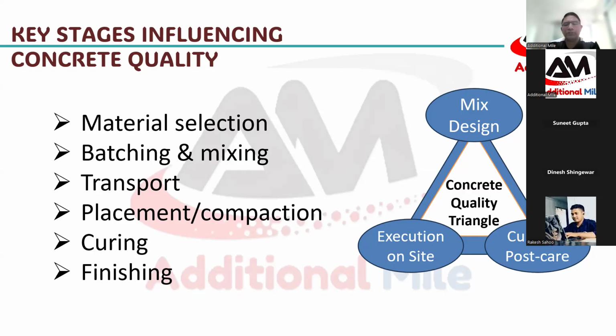Within these 2 hours are your mixing, transportation from plant to site, and pouring. These 3 stages have to be completed within the designed time. Even a slight delay will affect the concrete behavior or quality. It will start setting earlier, and there will be segregation inside, which you cannot repair. You can do nothing if that designed period lapses. Then placement or compaction also influences the concrete behavior drastically.